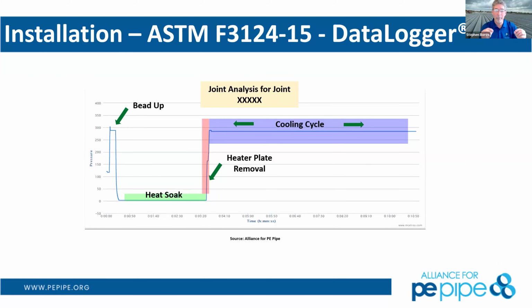Once you see that melt bead first coming up, then you can reduce the interfacial pressure holding those ends together, and you want no interfacial pressure during that heat soak. Now you're just putting all that heat into the polyethylene and melting it back to a certain point, several thousandths of an inch back in there over this whole heat soak time, which is, again, a known value for the size of pipe that you're using.